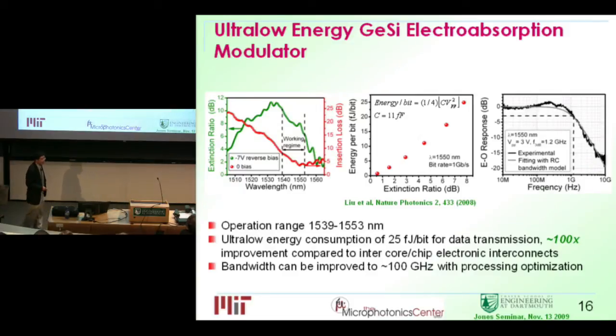So these curves show some of the performance. Let me guide you through that. This figure shows the extinction ratio, which means the on-off ratio of the modulator. So you want this one to be as high as possible. This red curve shows the insertion loss of the modulator. That's how transparent the device is when you don't apply the bias. So you want this one to be as low as possible. Overall you can work in a wavelength range of around 1539 to 1553 nanometers. So what's the significance of 1550?